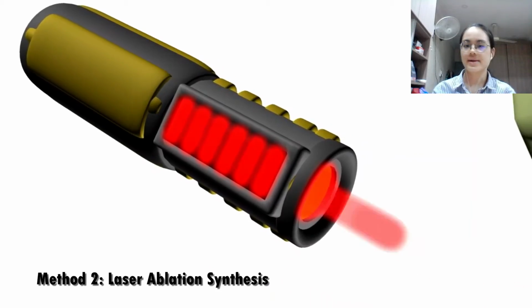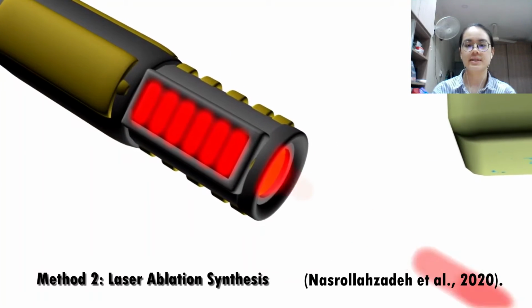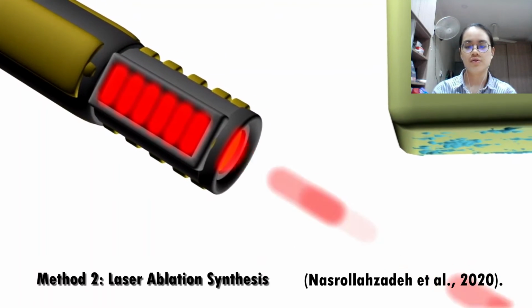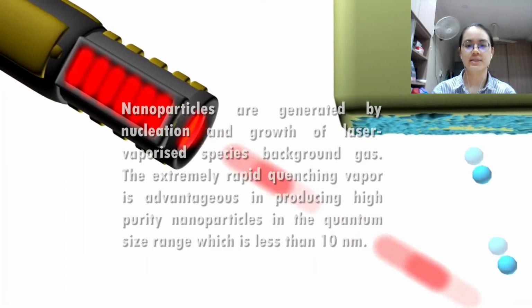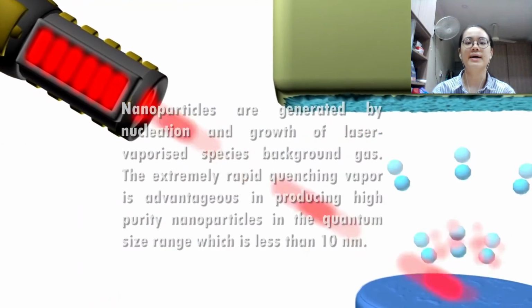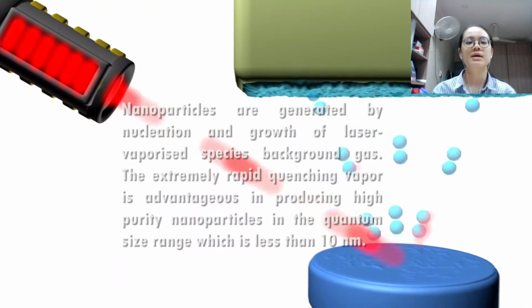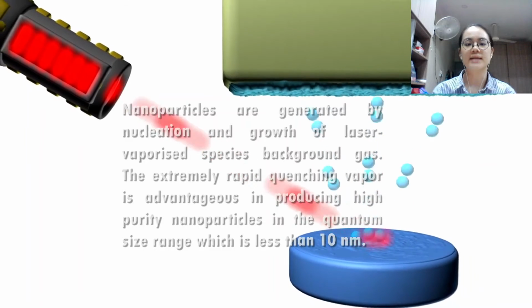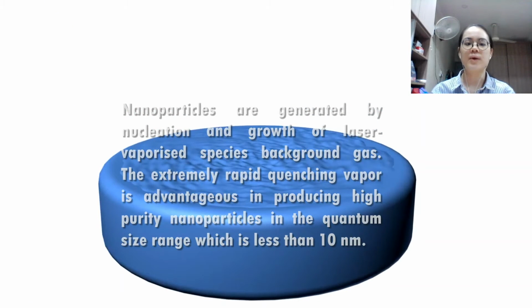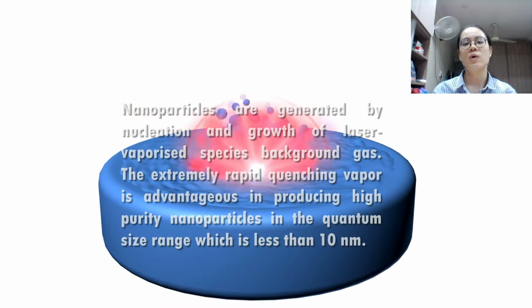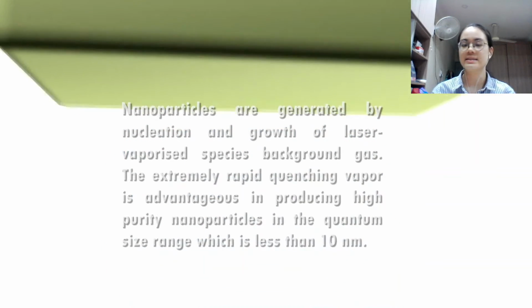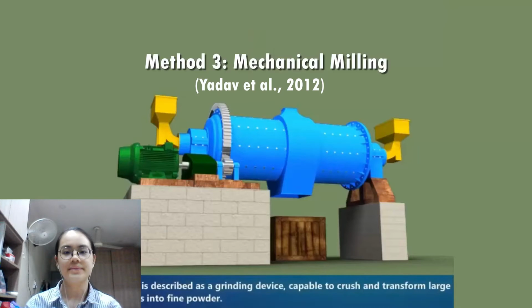Then the second method is laser ablation synthesis. For laser ablation synthesis, the nanoparticles are generated by nucleation and growth of laser-vaporized species in a background gas. The extremely rapid quenching of vapor is advantageous in producing high-purity nanoparticles in the quantum size range, which is less than 10 nanometers. And the third method is mechanical milling.